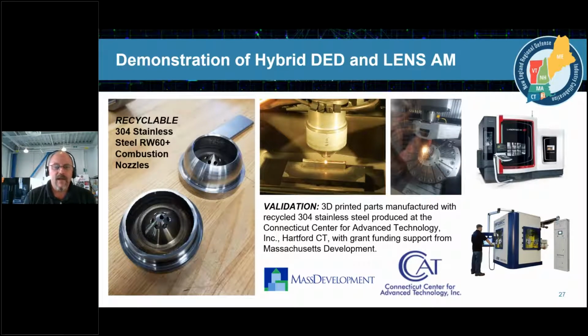And that indeed ended up with some success. We used directed energy deposition and LENS, two processes that CCAT has, to not only print some samples, but also print millable parts using some reference designs that they've been exploring. And that was quite impressive. And certainly was something well worthwhile from the standpoint of short funding science, ways to get things done quickly, demonstrate what's possible, and then start looking at what you need to fill in the blanks.